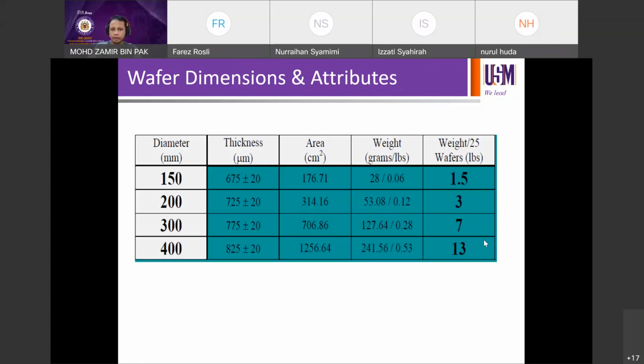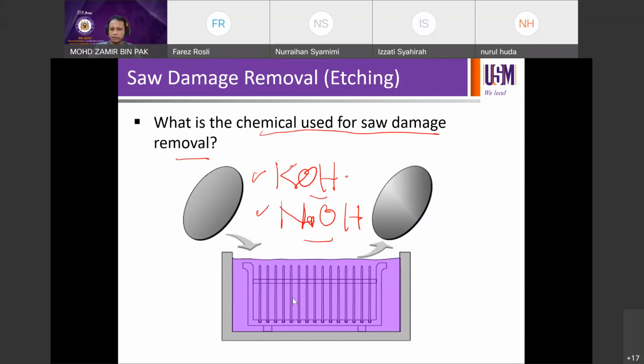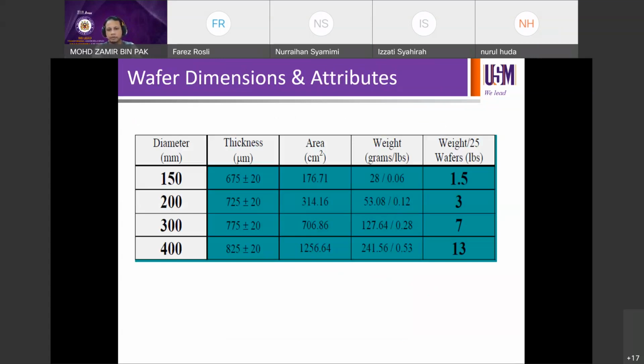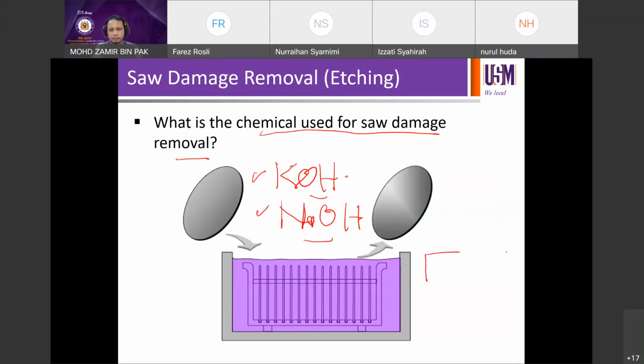There is a certain concentration that you have to use in order to remove the damage. Okay, if you use the concentration too low, then it's going to etch the surface into pyramids. And later we will learn about that in the etching process. So you normally have that kind of roughness after the slicing process, and you want to end up with a perfectly smooth surface. You want it to be smooth and damage-free. At first it is very rough, microscopically very rough. So you have to etch using a certain concentration in order to remove all the defects. Okay.